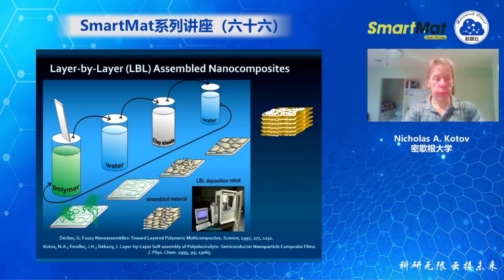the nowadays classical method of layer-by-layer assembly, which has been developed by Gerald Decher. We designed this method in order to make biomimetic composite materials. We started actually not from clay, but from graphite oxide. And in all the cases, we have very high contribution of interfaces and layered organization of organic and inorganic